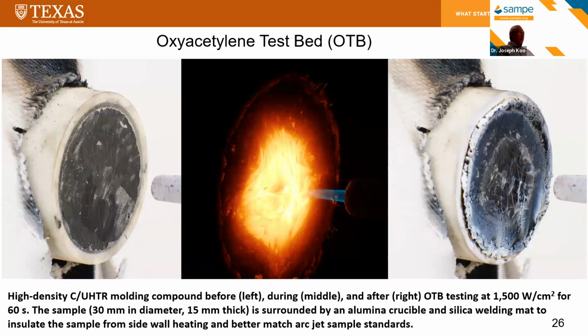Okay, this is an interesting showing of what we have done using OTB. On the far left, you can see a high density, roughly 1.41 grams per cc, carbon fiber UHTR molding compound before it was tested. In the middle, you can see during the testing, it is a very high heat flux that we are using, 1,500 watt per cm square for 60 seconds. On the right-hand side, you see how the material looks at the end of the testing.